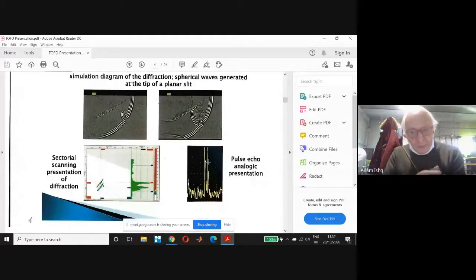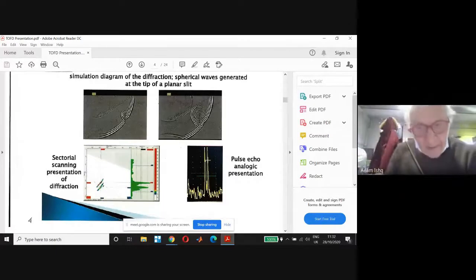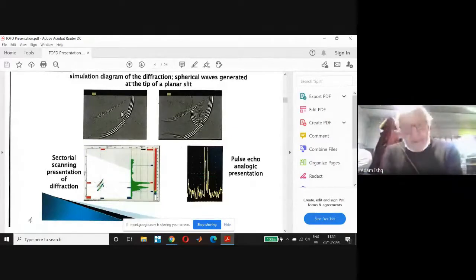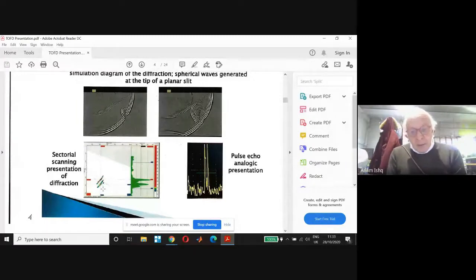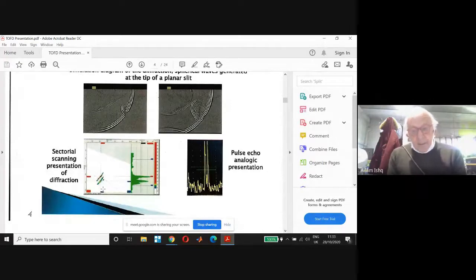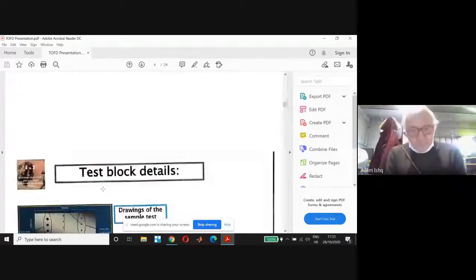On the right side, you see an example of how you see the tip of a crack with standard pulse-echo ultrasonic. You see two echoes, one from the upper tip and one from the second tip. This is if you have a high resolution probe, high resolution angle. Not always can you see a 3 millimeter crack with such resolution. On the left side, you see how it looks with another ultrasonic technique, phase array. Also here you see the upper tip and the lower tip. Phase array, different from time of flight, still has limitation due to the orientation, because phase array is at least again a pulse echo with different beams. Okay, now we go. Clear?